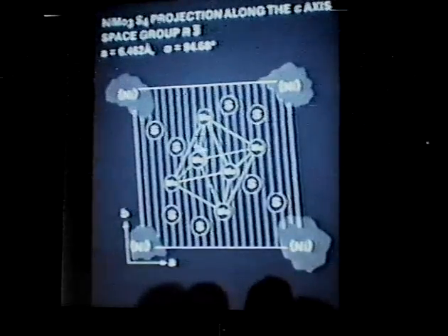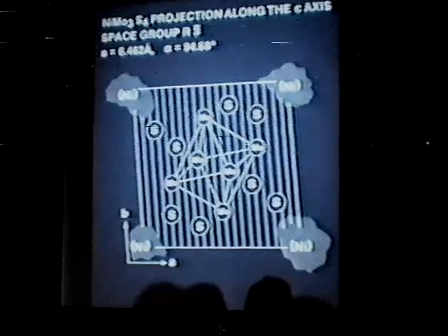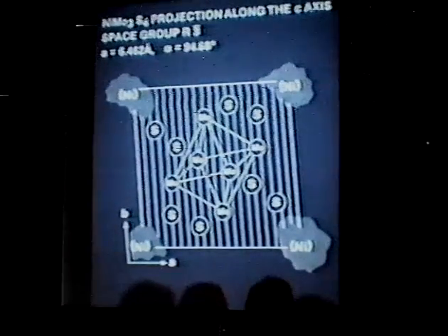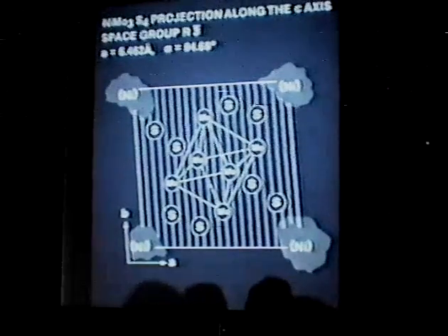by going through calculations like were illustrated at the first of my talk, you can estimate that about 40 or 50% MoO3 equivalent can be stored on a support of similar surface area. And if one can figure out how to get Chevrel phases dispersed properly on supports with 300 square meters per gram surface area, for example, we could up our activity some more, maybe by quite a bit. If it turns out that this model isn't correct, then we've maybe reached the limit of our improvement by way of extra metals loading and have to look elsewhere for other improvements in hydrotreating catalysts.